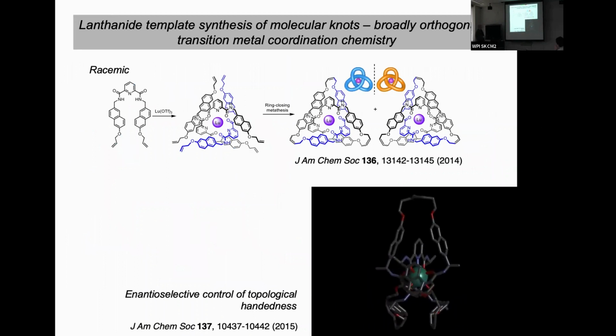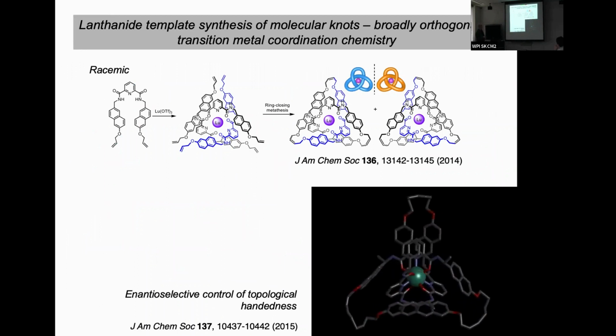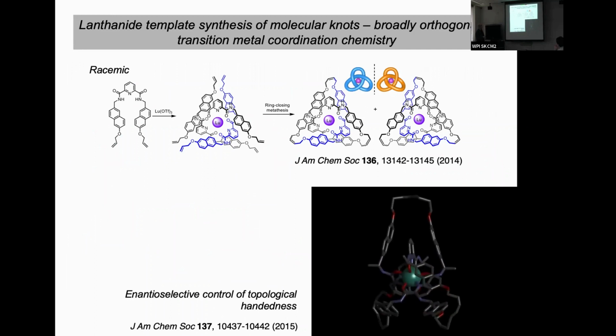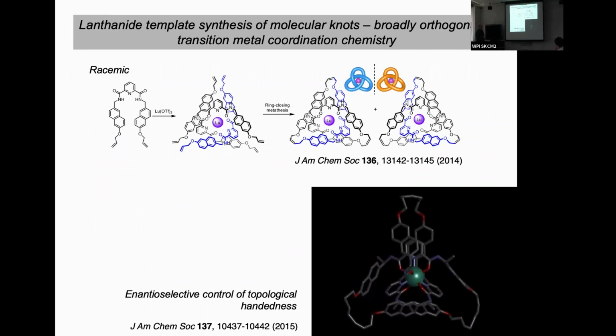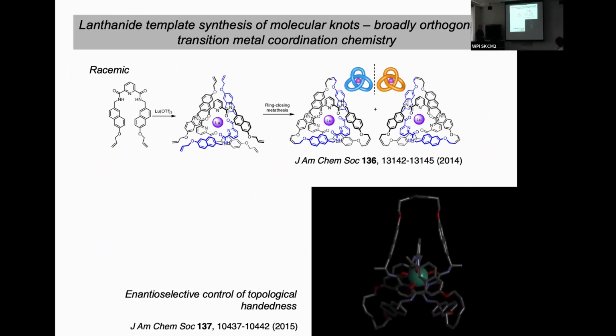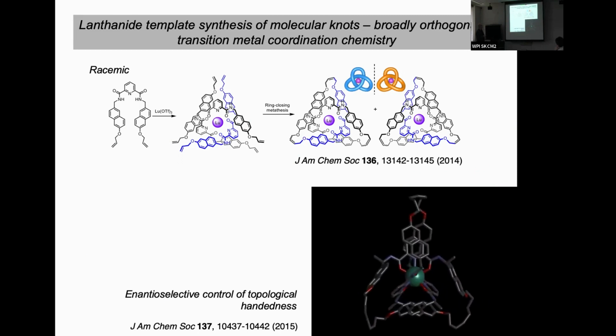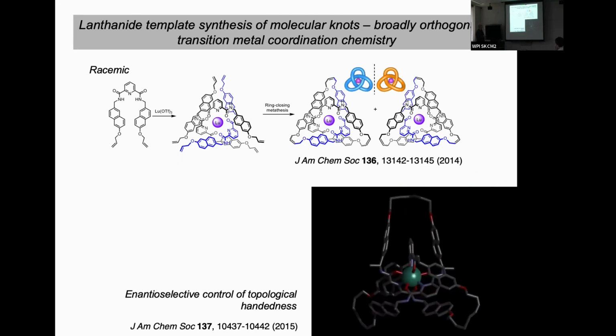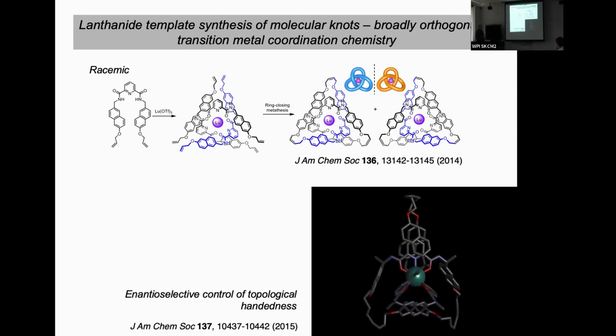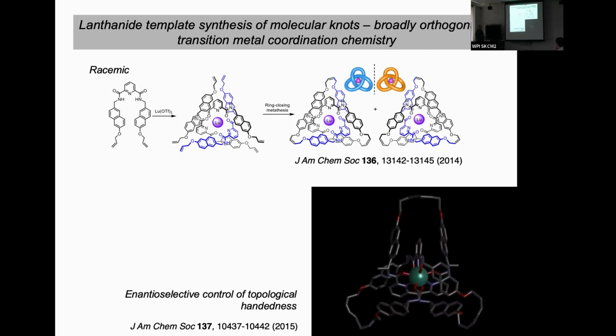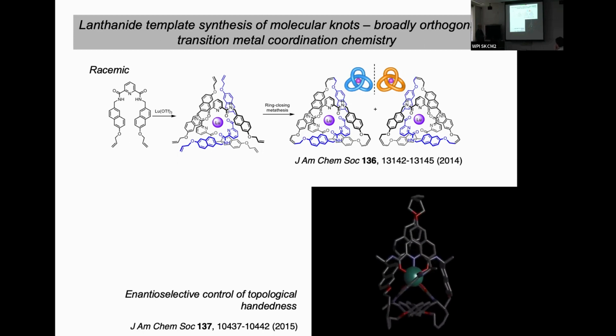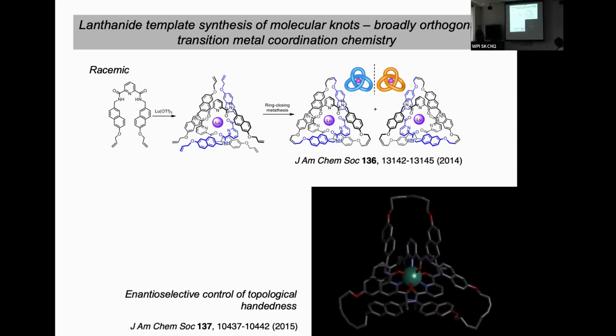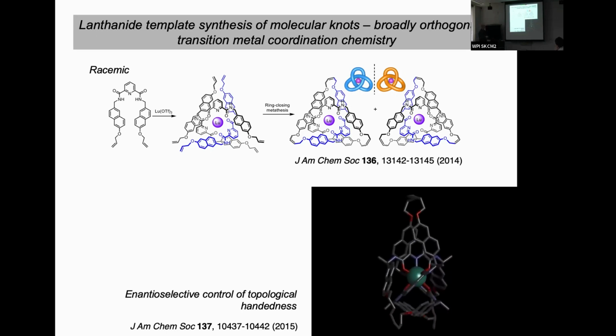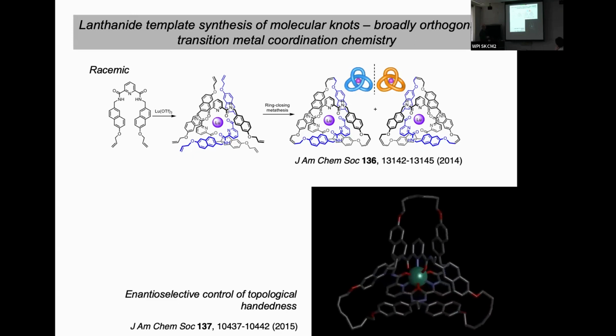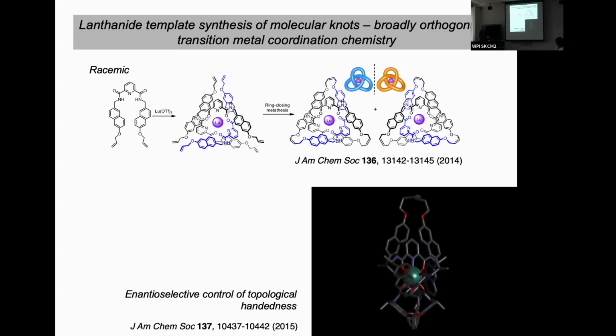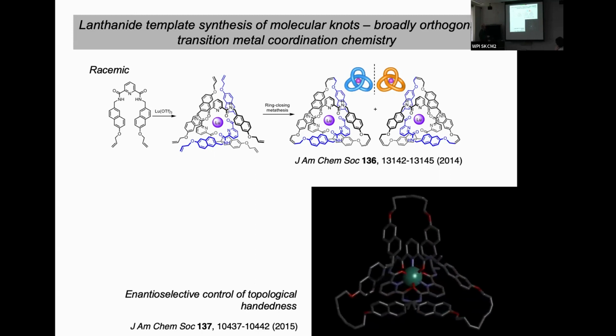So we can use not just transition metals to template the assembly of knots, but we've also used lanthanides to do that. If you take any lanthanide in its 3+ state, they'll assemble 3 of these ligands around them, coordinating to the 2 oxygens here and the nitrogen. So it's a 9-coordinate lutetium example here. Having these aromatic groups here organizes these strands so it holds these double bonds, these olefins, close together, so you can do ring closing metathesis to close the end groups here. And this will form trefoil knots. There's no chirality in these structures, so you'll form both enantiomers of the trefoil knot, so 2 mirror images.